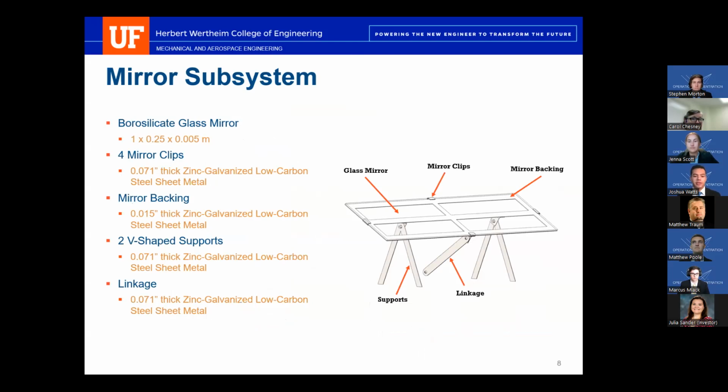Each mirror is 1 meter by 1/4 meter, and they're all made out of borosilicate glass. The reason borosilicate glass was chosen was because it has lower stress concentrations from thermal expansion and contraction with the change in temperature. The mirror is held onto the backing with 4 mirror clips. Attached to the mirror backing are 2 V-shaped supports that are welded on and then bolted. There are welded tabs that are bolted to the V-shaped supports, and then there's also a linkage that is attached to a welded tab. All 4 of the parts other than the glass mirror are made out of zinc galvanized low carbon steel sheet metal.